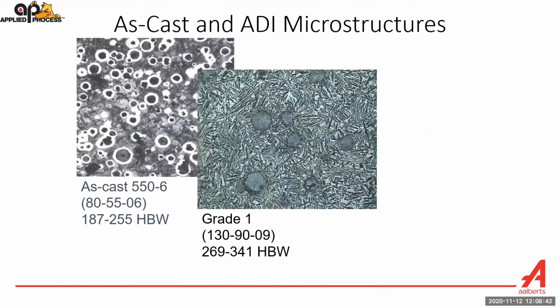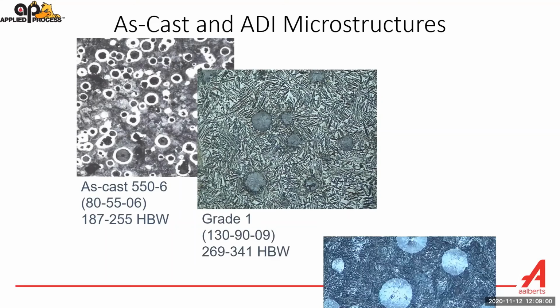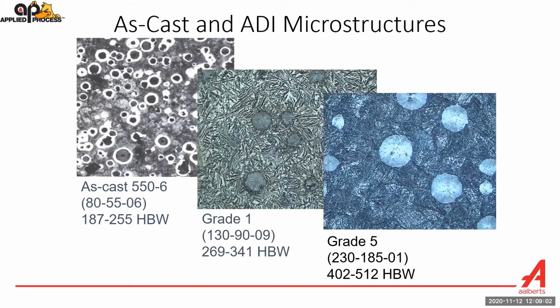After austempering to grade 1, the structure changes dramatically. Note though, we do not change the graphite nodules, even though there might be a different quantity of them. This is a different sample, but everything else in between the graphite nodules changes. It's that ausferrite or acicular structure. And then that's what grade 5 ADI looks like. It's a finer structure and a slightly different combination of austenite and ferrite.